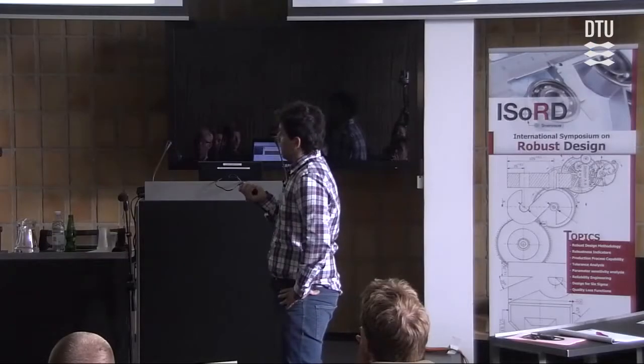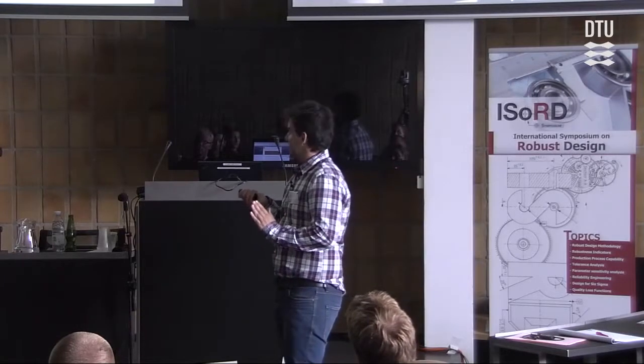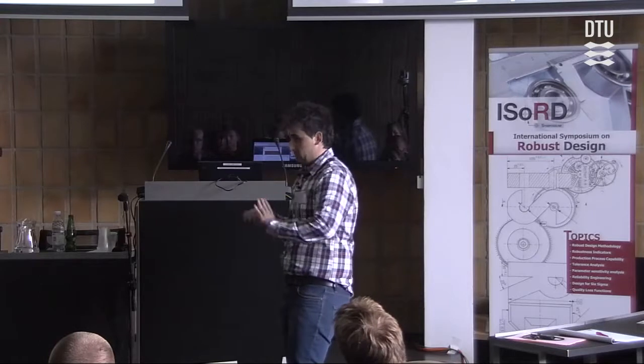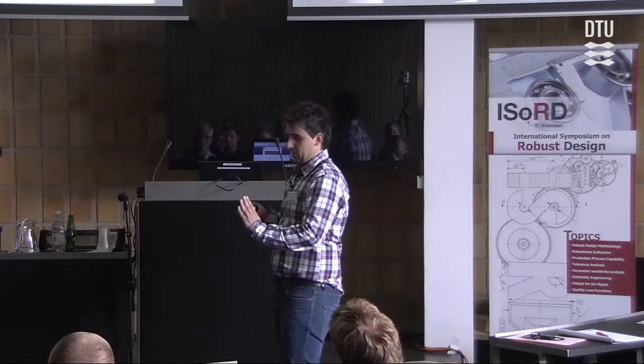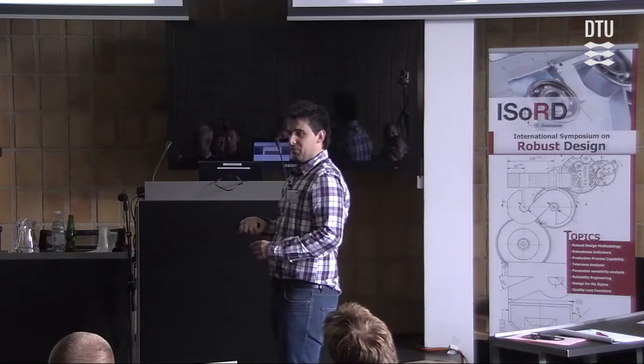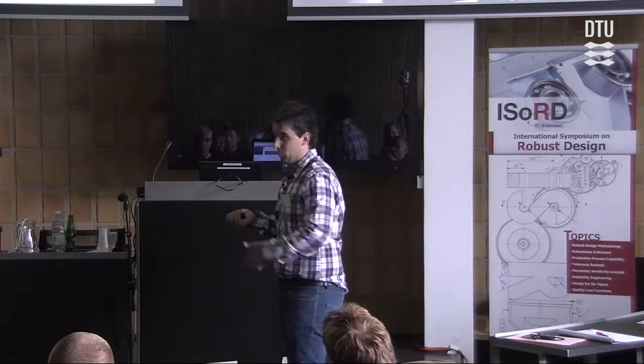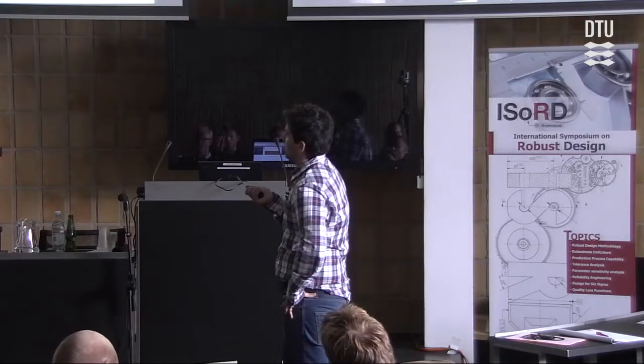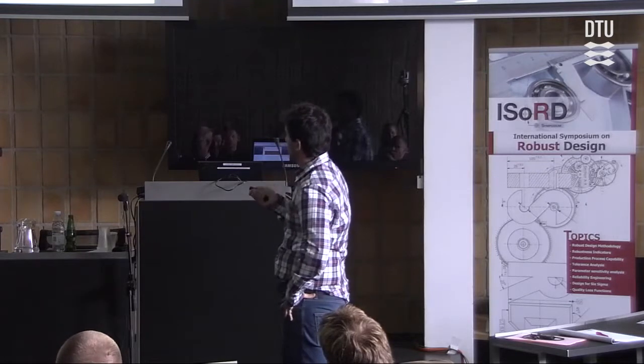So you can see that solution 3 is already gone because of the sensitivity. So it was not good enough. But you realize that solution 1, which is machine material A1, meaning stereolithography equipment, specifically that machine and in those specific conditions, with the part orientation only in vertical and the part location only in the center of the machine, is a bit tricky. Because then you can say, okay, I can use this machine to produce my part, but the reality is that you can only produce in the center. And how many units you can produce in one single print, the cost raises very high. And the digital quality needs to be medium at least.